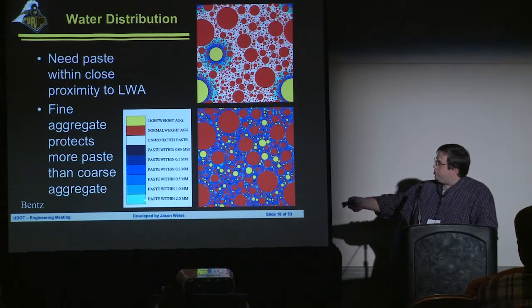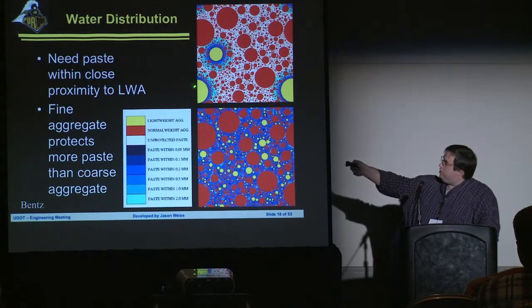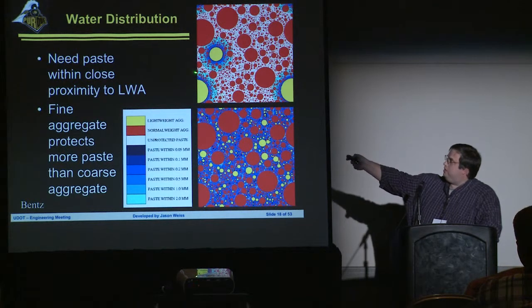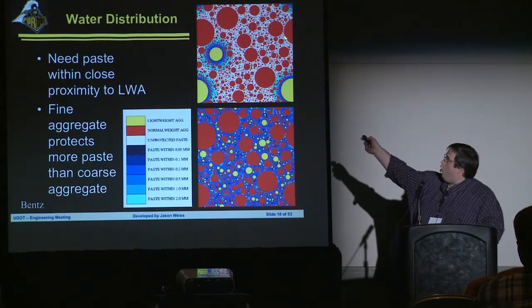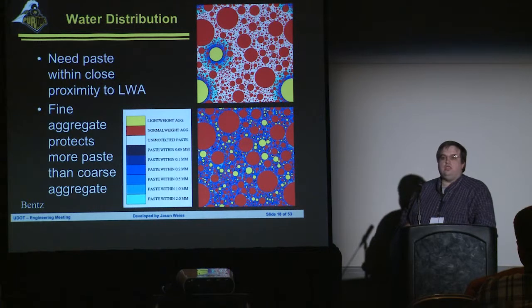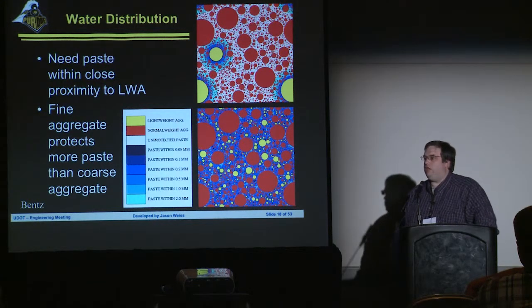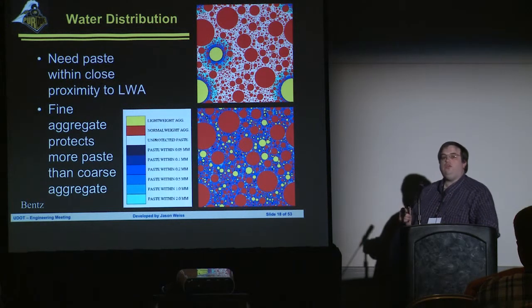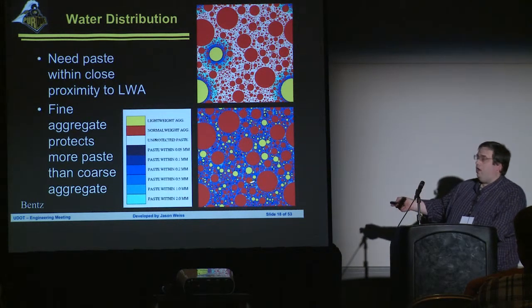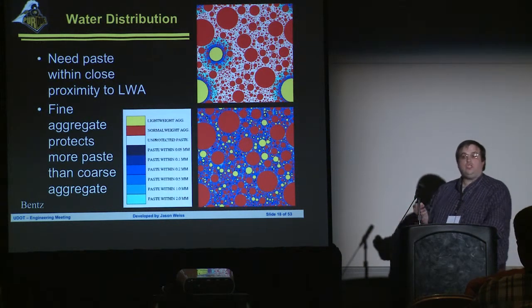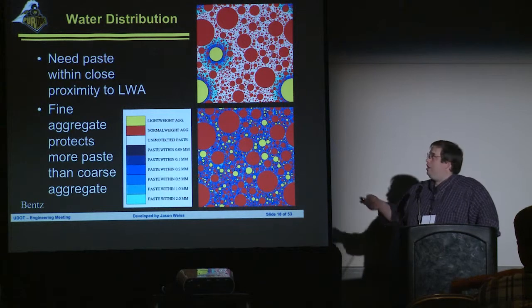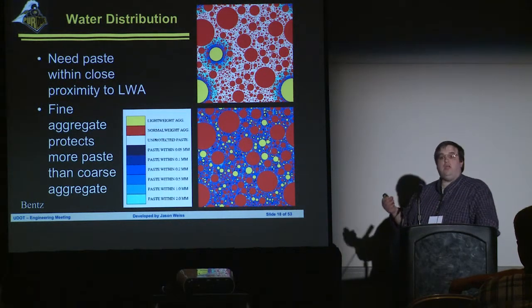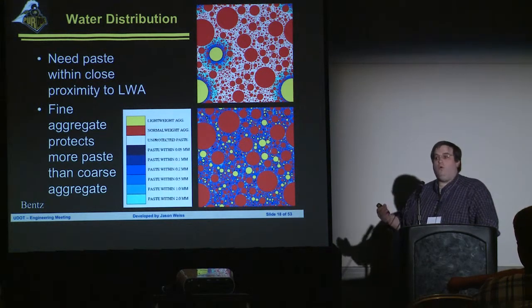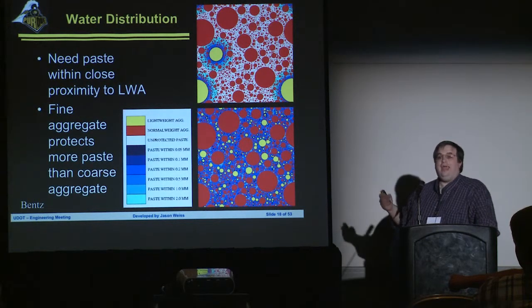The 2 millimeters is shown here as aqua. And what you can see is from this big coarse aggregate, we can essentially assume the water gets out into this range. But there's a whole bunch of the matrix that didn't get that water that came from the lightweight aggregate. If you use the sand, that water gets distributed. So the question was, why does this happen? This matrix becomes very, very dense. So if you've got a 0.3 water to cement ratio, you can't get this water to travel after about 18 to 24 hours.